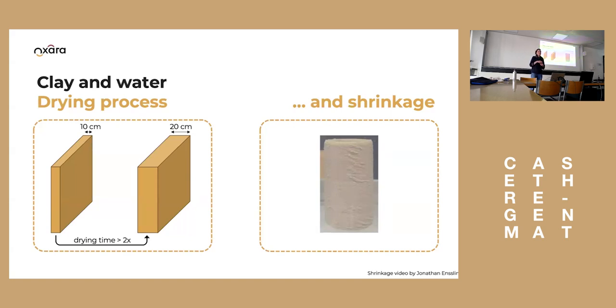And then along with the drying comes the shrinkage. So you have the water around these clay particles. And first, maybe the clay particles don't touch each other because they're separated by the water. And then once the water starts to dry and to evaporate, it leaves the system, and that leads to a volume change. And that volume change can be quite drastic, as you can see here in this video, where you can see how a clay cylinder shrinks. I can play it maybe one more time.